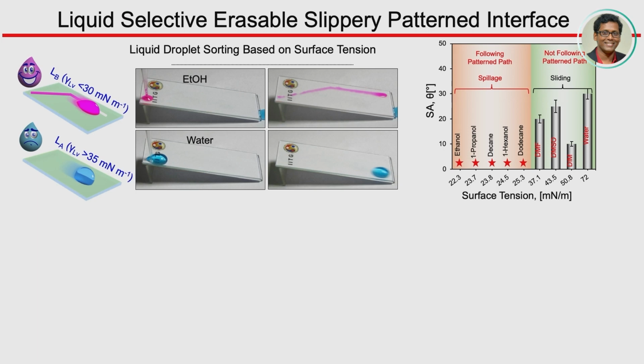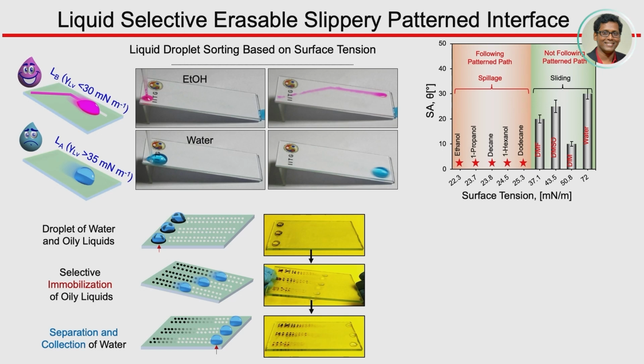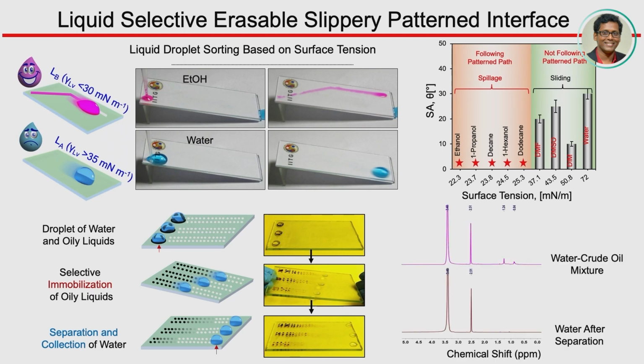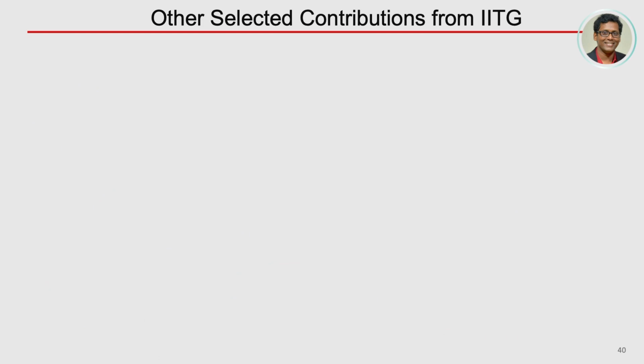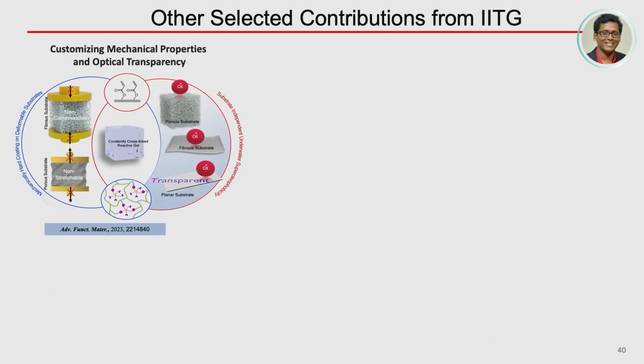And you can see these liquids can follow this path, and this group of liquids can follow this particular path, right? Not only that, you can have an array of these spots, and you put an oil and water droplet together. You will see the cleaving of this oil droplet from water, and you can collect the oil-free water. So it could be something like an oil catcher, right? And depending on the concentration of the oil, you can see the length of this oil strip is varied. So qualitatively also you can tell whether the contaminated water has more oil or less oil. And many other things are possible.